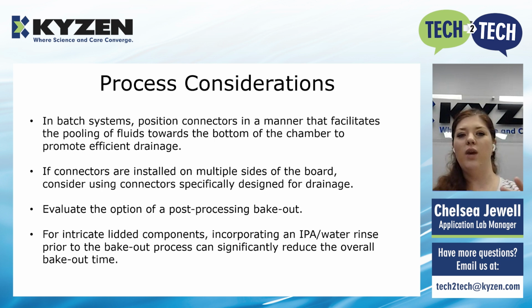So what we try to say is, if you can, position those connectors facing downwards so you don't have that cupping action on the top of the board. Obviously, connectors can be on multiple edges and multiple places on the board, so understand how that board looks in the machine to prevent that cupping action. If it is unavoidable, I've seen multiple connectors that are designed specifically to help with drainage, whether that's notches on the side or it's not fully sealed at the bottom. It depends on what type of connector you're using, but some considerations to help promote drainage can help very much, so you have an efficient drying process in the machine.